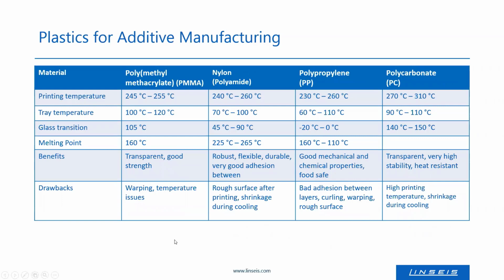Here are the next used plastics for additive manufacturing. So PMMA is also used rather often, as well as nylon. Here, printing temperatures of PMMA are lower than, for example, those of nylon. And here again, a heated tray is necessary. Why it is necessary, I will explain a bit later. In this table, you also always see the glass transition range and the melting point of the material, which is also important for the printing process. I will describe it a bit later. Here you see, for example, that the glass transition of PMMA is at much higher temperatures than that of nylon.